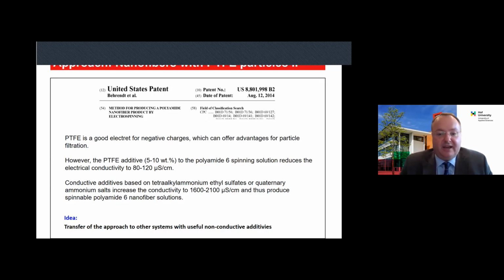What you can do is add some additives like tetraalkyl ammonium ethyl sulfates. And then you can increase the conductivity to roughly 1,600 up to 2,000 microsiemens per centimeter. And therefore, the result is that you achieve spinnable polyamide 6 PTFE solutions. And maybe why I present this topic here: at first, it's important to know that we can generate polyamide nanofibers with implemented PTFE particles. But in my opinion, this approach with conductive additives is also applicable to other problems, to other issues.